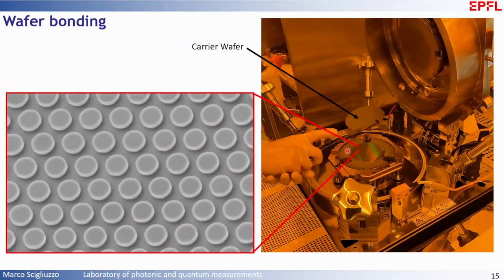Then there is the bonding. So we are able to make the phononic shield. About the bonding, we use this bonding technique where you activate both surfaces and you just place one wafer on top of the other. This wafer bonding will apply some pressure in vacuum and temperature, and that's how the two wafers are effectively bonded.